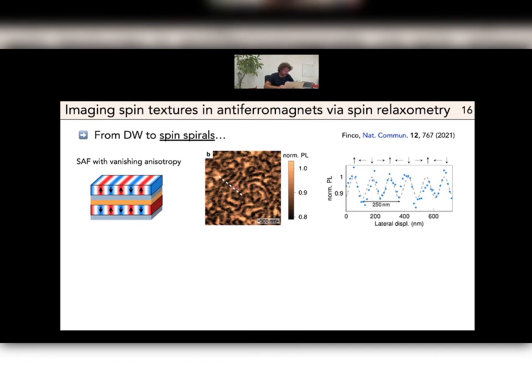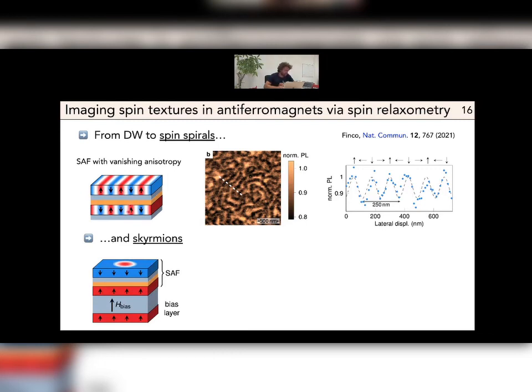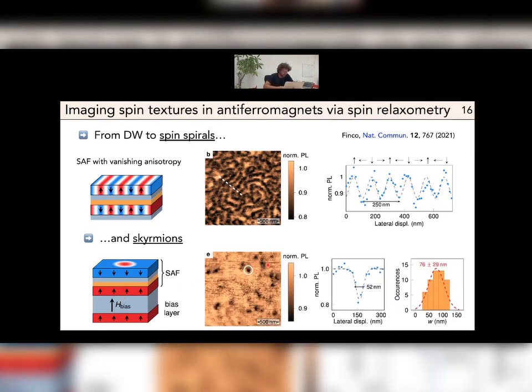This spiral is interesting because, as soon as you have this spiral state, you can try to bias the spiral to obtain skyrmions. For doing that, you add a bias layer here that will act as an internal magnetic field that will collapse or turn the spiral into skyrmions, as proposed in a first paper from Vincent's group. And this is indeed what we see. After putting the bias here, we have isolated dark spots that correspond to magnetic skyrmions. At the location of a magnetic skyrmion, we have an excess noise, and this is the way we can observe the skyrmions in our sample.